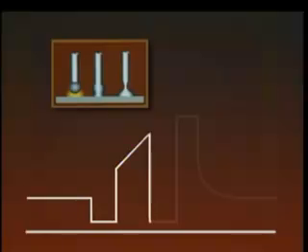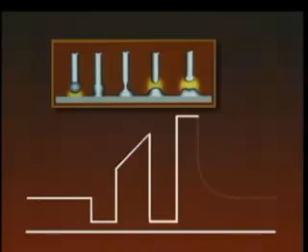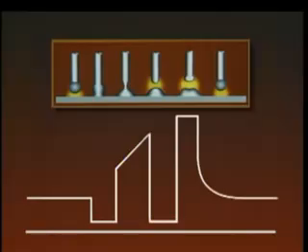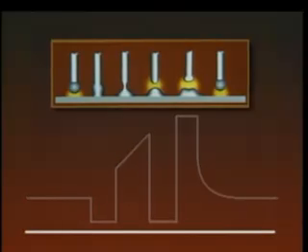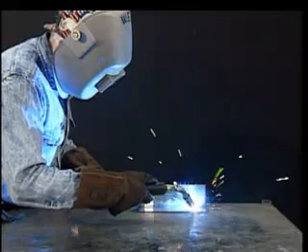Prior to fuse separation, the current is reduced in millionths of a second to reduce the explosive nature of the molten metal transfer. A plasma boost current is then imposed on the arc. It melts the electrode back. This reduces spatter and fume generation. The arc current is then reduced to the background level in a controlled manner, reducing weld puddle agitation. It is the instantaneous control over the current that eliminates the highly violent and explosive energy of short arc MIG welding.